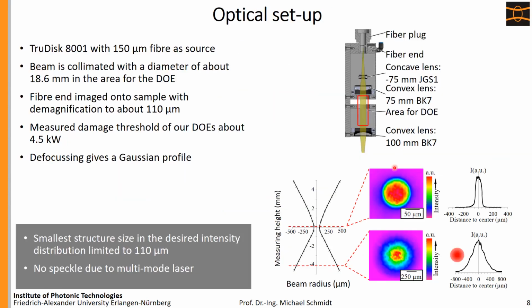So we built this into a laser head that we have here. So we plug in the fiber. In this case, we used an 8 kilowatt laser, and we have an area where we put in our diffractive optical element. And you can see here, if we have the normal beam shape, so without the diffractive optical element, in the area of the focus spot we have a top hat or at least a super Gaussian profile. Whereas if we detune, so if we go to here, -4 millimeter from the focal point, we go more and more to a Gaussian profile.